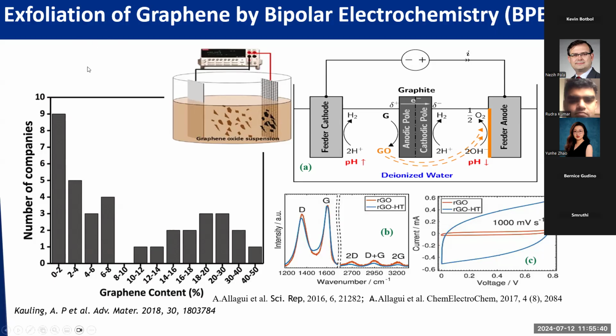He did materials characterization and found that only 1 company had a real graphene content, really 2D materials, at about 40 to 50%. That means the other half is not graphene, they are nanoplatelets. And some companies, 9 companies, claim they are selling graphene but only have about 2% graphene content. The majority of companies have less than 30% graphene content, even though they say they're selling graphene. So we have to solve this problem if we want to integrate graphene on our micropillar array carbon MEMS. We need 2D materials. We don't need the nanoplatelets. So we looked at the literature.